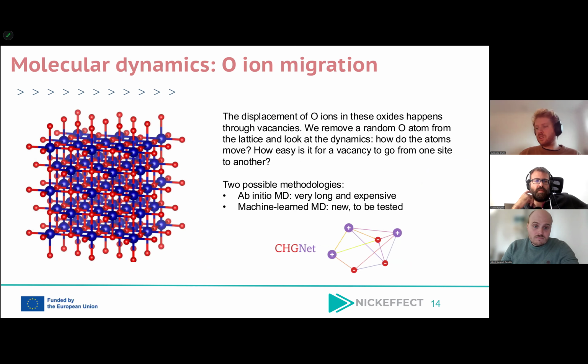And so to better understand that, we decided to use molecular dynamics to understand how the oxygen ion migration happens in these systems. And so we consider the cobalt oxide and the nickel oxide crystals, and we know that in these systems, the oxygen ions move through vacancies. And so what we did is we considered a big supercell, a big piece of these systems. We removed one oxygen atom in the simulation, and then we let the system live. We looked at the dynamics, and that was to understand how the oxygen atoms move and how easy it is for the vacancy to actually go from one side to another in the lattice and diffuse in the lattice.